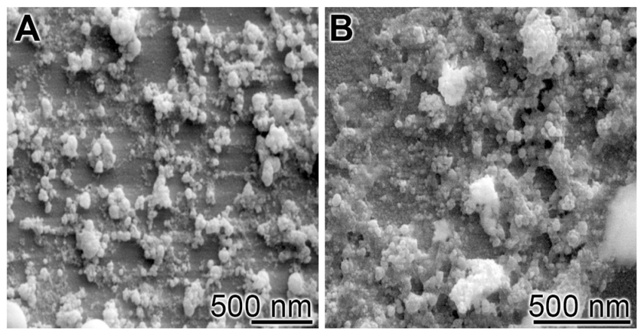Because of the lower fabrication temperatures used in sol-gel synthesis, there is a greater level of control on the composition and homogeneity of the product. In addition, sol-gel bioglasses have much higher porosity, which leads to a greater surface area and degree of integration in the body. The third method is microwave synthesis of bioglass, which has been gaining attention in recent years. Microwave synthesis is a rapid and low-cost powder synthesis method in which precursors are dissolved in water, transferred to a microwave oven, and irradiated. The resulting amorphous powder is then filtered, dried at 80 degrees Celsius, and calcined at 700 degrees Celsius.